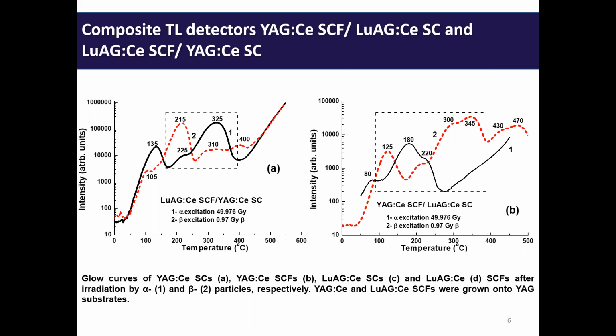As mentioned above, alpha particles of the 241 americium source, with a typical pathway in the lutetium aluminium garnet and yttrium aluminium garnet hosts of 10 to 12 micrometers, are fully stopped in the single crystal film parts of a composite detector with a thickness of several tens of microns, while beta particles of the 90 strontium source with an average energy of 1.1 megaelectronvolts can penetrate the whole 1.3 millimeter thick yttrium aluminium garnet and 0.8 millimeter lutetium aluminium garnet single crystal substrate. Therefore, the TL signals from single crystal films and single crystal parts of both composite detectors under study correspond mainly to the registration of alpha particles and beta particles, respectively.